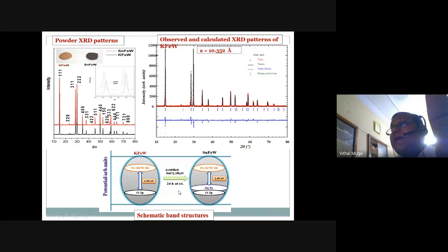Then you see that its band gap energy changes. This is a schematic band structure, obtained from the DRS spectrum, diffuse reflectance spectrum. Now if you look at the KFEW, the conduction band is made up of iron 3d and tungsten 5d. The valence band is made up of oxygen 2p. Now when you dope with the tin, you see that this oxygen 2p is now overlapping with the tin 5s. From 1.95 it goes to 1.45. A reduction in the band gap of about 0.5 is highly significant. This was actually the highlight, that we could reduce the band gap energy from 1.95 to 1.45.